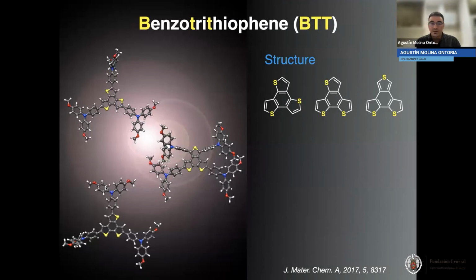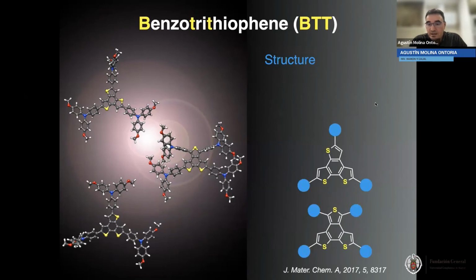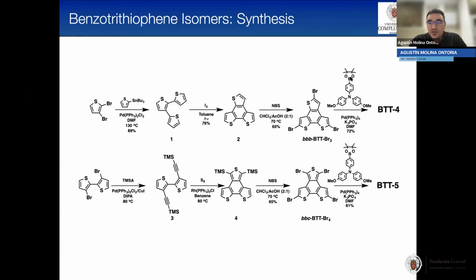Well, encouraged by these extraordinary results, we decided to continue exploring the isomerism effect on the photovoltaic performance. For that, we chose another two central scaffolds, BTT central scaffolds, and we introduced the same electron donor group that displayed the best efficiency with the methylammonium perovskite. Well, the synthesis of these molecules is quite different. So for BTT4, we started with this dibromothiophene. We performed a two-fold Stille coupling, then oxidative photocyclization. We get the BTT central scaffold. We brominated at the alpha positions of the thiophene rings. We performed a three-fold Suzuki cross coupling just to get BTT4.